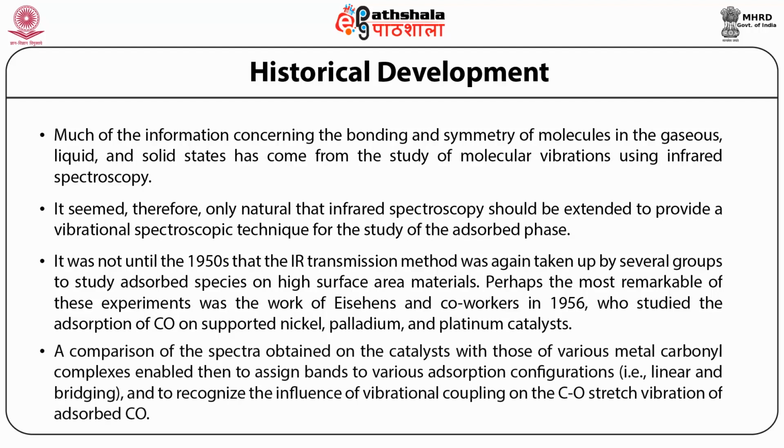A comparison of the spectra obtained on the catalysts with those of various metal carbonyl complexes enabled them to assign bands to various adsorption configurations, that is, linear and bridging, and to recognize the influence of vibrational coupling of CO stretch vibrations of adsorbed carbon monoxide.